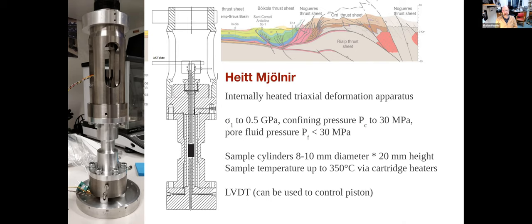And this is a rig that is an internally heated triaxial deformation apparatus. It's a complete new design, actually, Edinburgh exclusive, I would say. And I'm really proud of this. We have managed, actually. So this is the difficulties. I have 2 minutes. I want to talk about difficulties in this, actually. The trick is we need to pressurize this much higher. We want to, and we're not quite there yet. We can get to 30 MPa at the moment, maybe 50. But at the same time, we want to heat to 350 degrees Celsius.